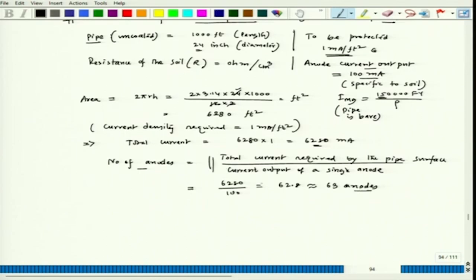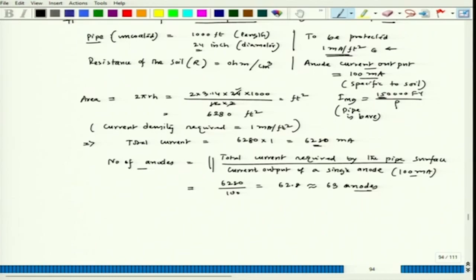I remember when we use this formula, this 100 milliampere current output is for a single anode. Now if we use multiple anodes and put them at a different distance, let's say 5 feet or 10 feet or 15 feet, there should be some correction factors, but roughly those correction factors can be taken as the same as the number of anodes. For example, if we use 4, the correction factor also becomes 4. But here we are not using that specific correction factor. So we are simply using that if one single anode gives 100 milliampere current, then the 63 anodes would give you 63 into 100 milliampere, which is the total current required to meet this current density. So this is the way to calculate the number of anodes.